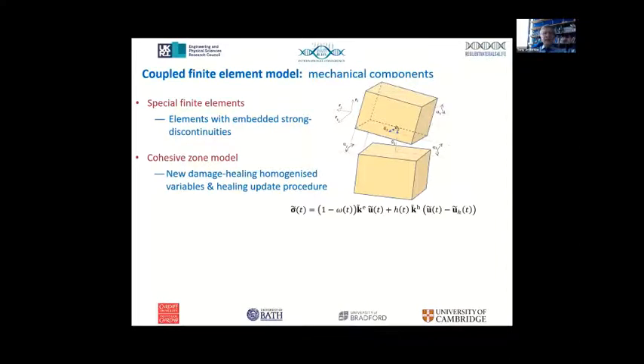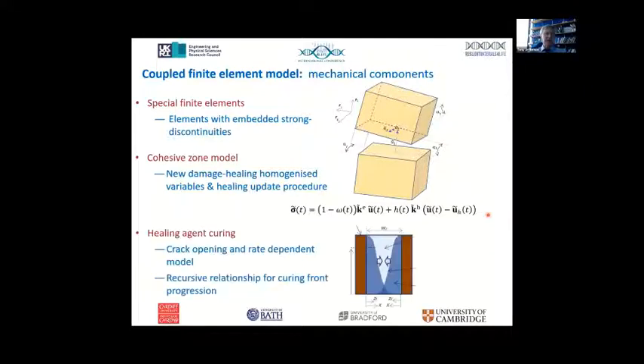We have come up with a new form of cohesive zone damage healing model. Now, you will see many models that have something like traction is one minus damage parameter, no damage or fully damaged, times stiffness, relative displacement, plus amount of healing, stiffness of the crack material, relative displacement, something to represent the cured material in the crack. This form and fairly similar forms of equation have been used by many. The challenge is how to actually get the evolution of these terms. Not so easy. I'll say a bit more about that.